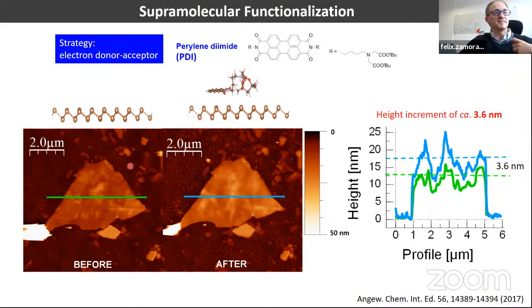And then we treated this substrate with a THF solution containing the molecule by drop casting. What we observe from here to here is that we increase the height of the initial layer by 3.6 nanometers, meaning that we have something on the top of this layer.